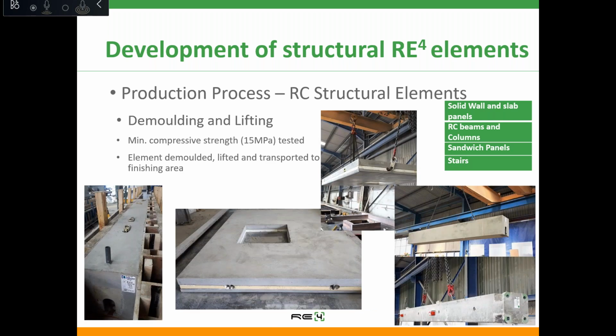Okay, the next stage of the production process is demolding and lifting. When the concrete reaches 15 megapascals, we can lift the panels. The strength of concrete is tested by testing two cube specimens, and if the strength is above 15 megapascals, then the panel or the element is demolded, lifted, and transported to